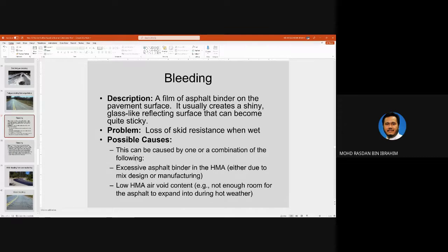So possible causes are excessive asphalt binder in the hot mix asphalt, too much bitumen. So you can see the bitumen, the aggregate goes down into the mix, and then the bitumen rises. So it has lots of excess bitumen. Or it can occur because of low air void content. So not enough room for the asphalt to expand during hot weather. So the asphalt expands to the surface of the pavement.